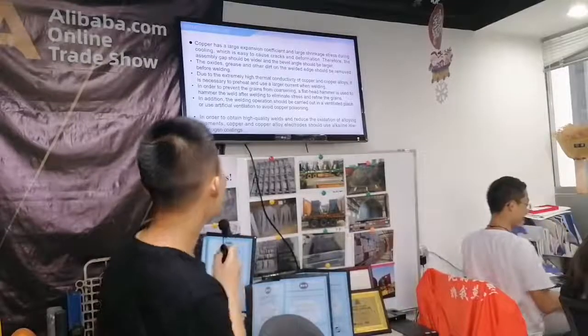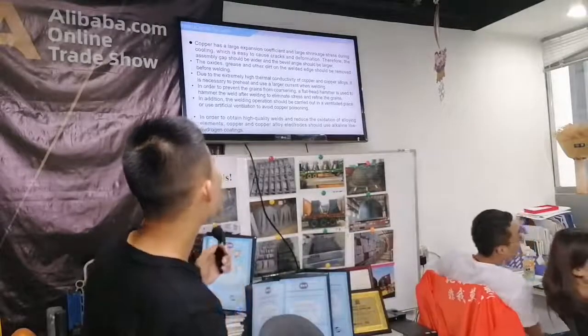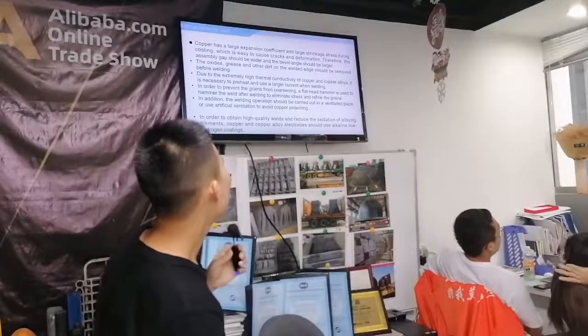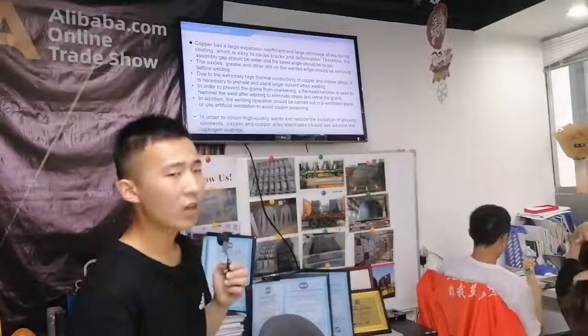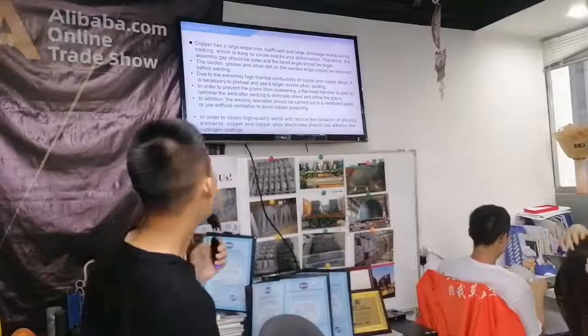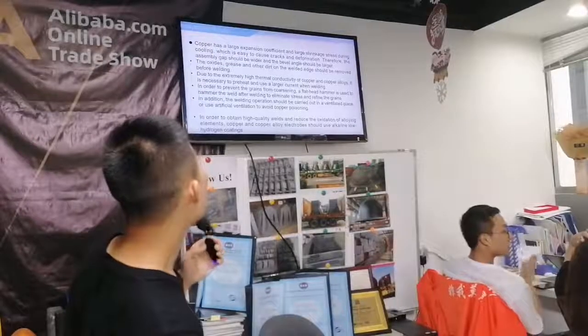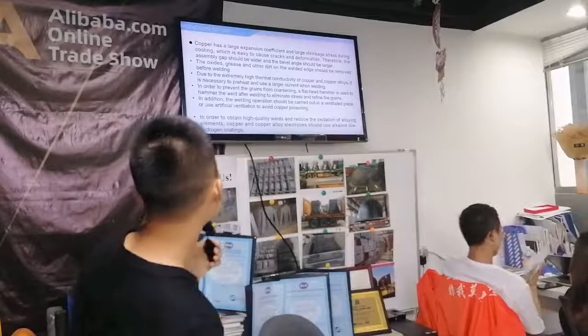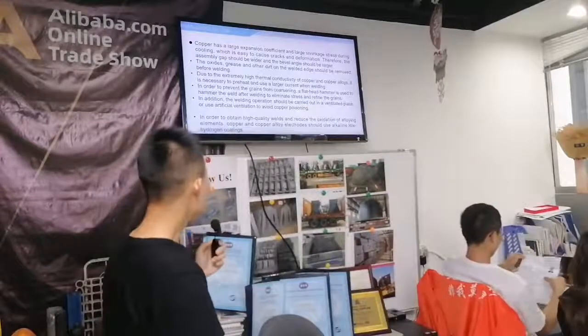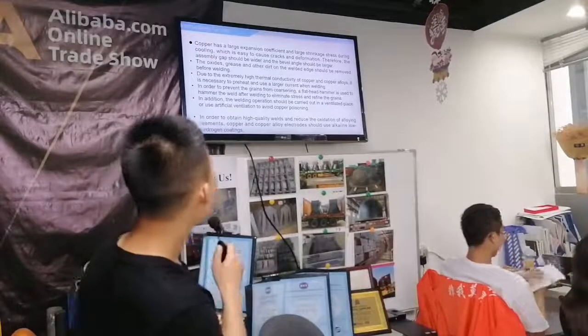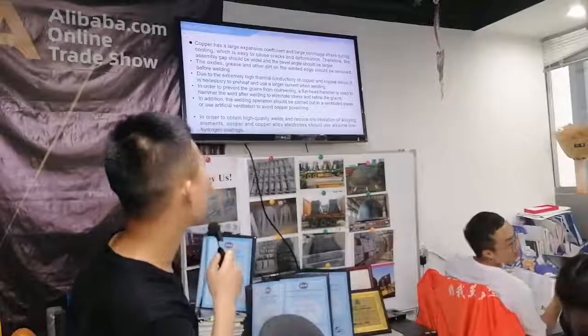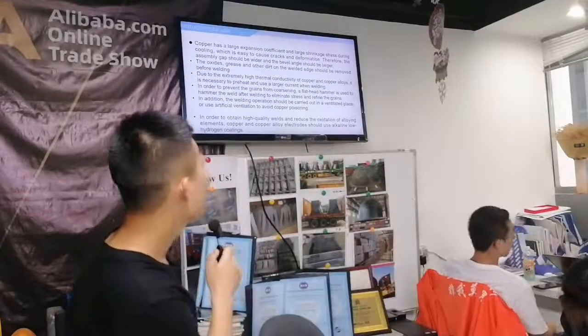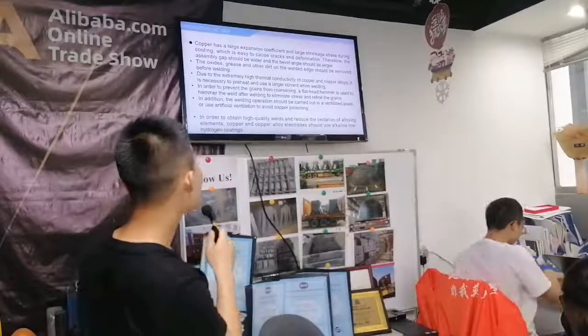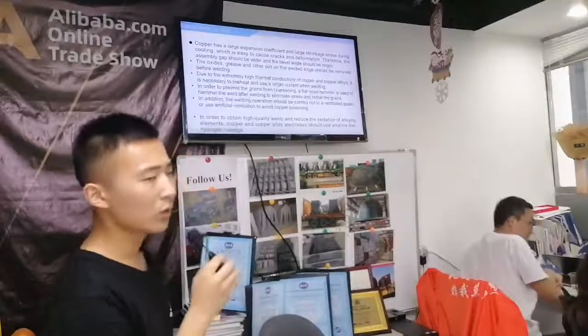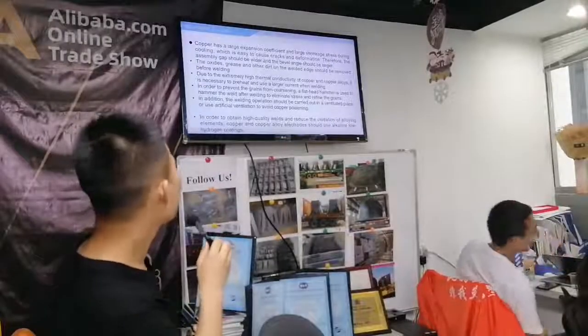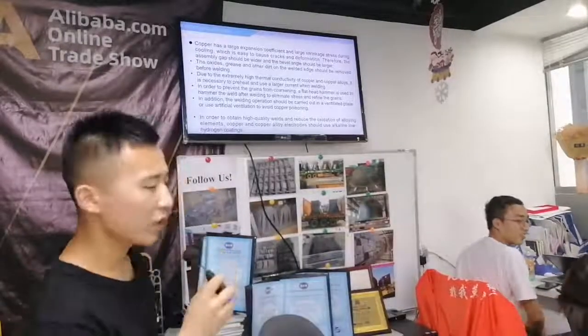Three, in order to prevent the grains from coarsening, a flat head hammer is used to hammer the weld after welding to eliminate stress and refine the grains. Four, in addition, the welding operation should be carried out in a ventilated place or use artificial ventilation to avoid copper poisoning. Five, in order to obtain high quality welds and reduce the oxidation of alloying elements, copper and copper alloy electrodes should use alkaline, low hydrogen coatings.